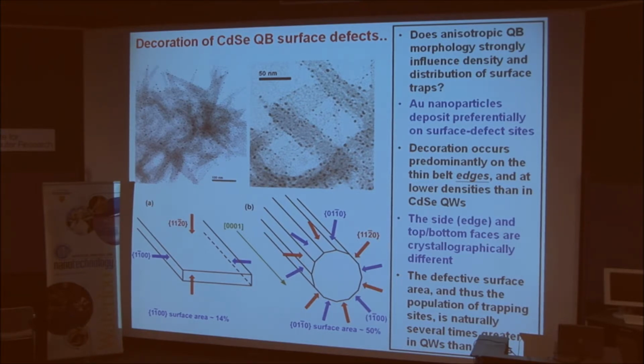Well, there are other possibilities that I'm going to explore momentarily, because although these are crystallographically different, the differences are very subtle. Both the top and bottom faces and the side faces are nonpolar. They have equal numbers of cadmium and selenium atoms. The structures are subtly different, but not markedly different. So it's hard to push that crystallographic argument very far. It seemed to us there must be some other reason that these top and bottom faces are particularly well passivated.